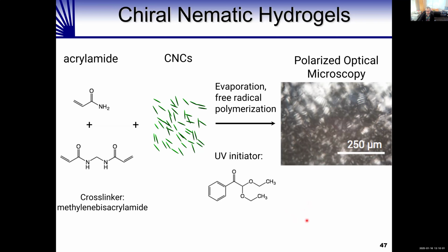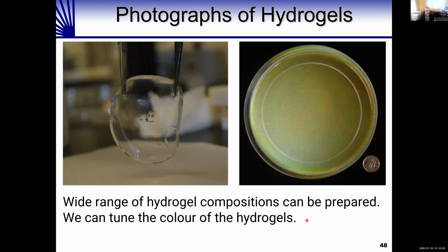Shown here are two hydrogels we prepared. On the left is one where the cellulose nanocrystals have a helical pitch that is longer than the wavelength of visible light, so it's reflecting infrared light. On the right is one that is reflecting visible light because the helical pitch of the cellulose nanocrystals is on the order of the wavelength of green light.